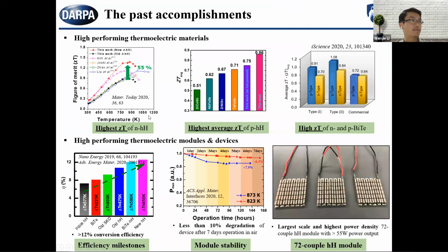So far we have made a lot of achievements. We have really improved the ZT of different types, like half-Heusler and bismuth telluride materials, with excellent ZT compared to state-of-the-art results. And we also made different scales of thermoelectric modules, and improved the conversion efficiency from about 6% to 12% that we have published so far.